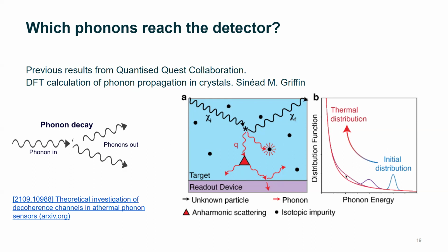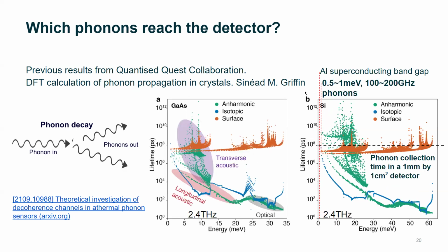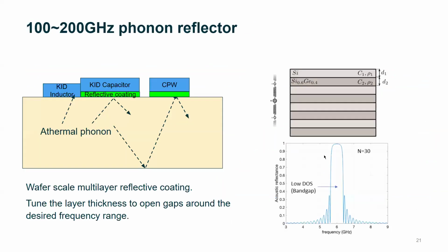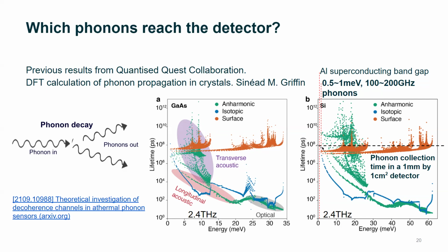We want to understand how phonons propagate and where on the spectrum we stand when we build a detector, so then we know what phonon energies we're going after. This is the calculation by Sinéad in our group. She did the DFT calculation that shows the different decay modes and lifetimes of different types of phonons. Overlaid on top of it, I can draw a line for a typical phonon collection time in a 1 millimeter by 1 centimeter square detector, and look for what the energy scale is. From usually hundreds of microseconds, the phonons will all decay into this 0.5 to 1 milli eV range, or say 100 to 200 gigahertz phonons.